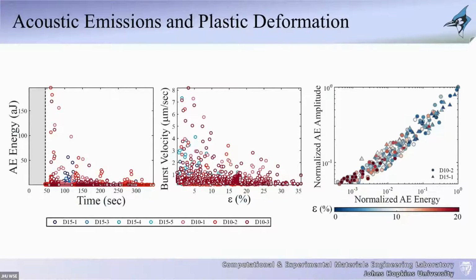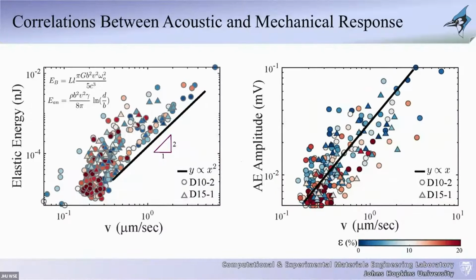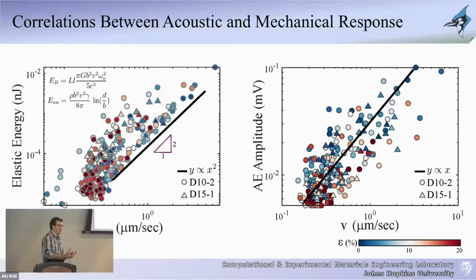I should say all of this is actually brand new work that Mustafa has been working on. So this is still unpublished, and we still are doing a lot of analysis on these data. Another intriguing thing with these types of calculations is that you can go into literature. Literature has tons of theories associated with acoustics related to dislocations, and none of them have been measured, none of them have been quantified. But this allows us, going down to the scale of microns, to go down to the scale of individual defects, and to quantify those types of theories. Are they correct? Are they not? Do they represent the behavior, or do they need a significant amount of understanding?